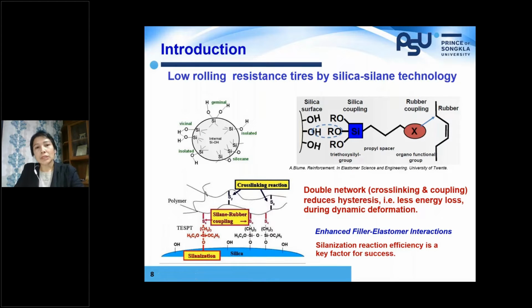When we talk about low rolling resistance tires, we need to move from carbon black filler to silica-silane technology. And on the silica surface, we have numerous silanol groups that bring some difficulties in mixing. And this silanol group has 3 different forms: isolated, vicinal, and geminal silanol groups, which have different reactivity. So when we react these silanol groups with a silane coupling agent, those different forms of silanol group will also react at different rates.